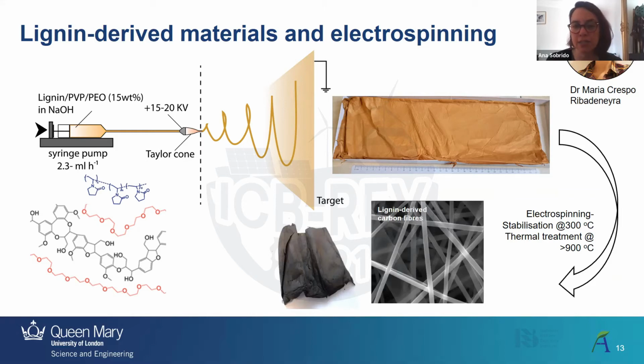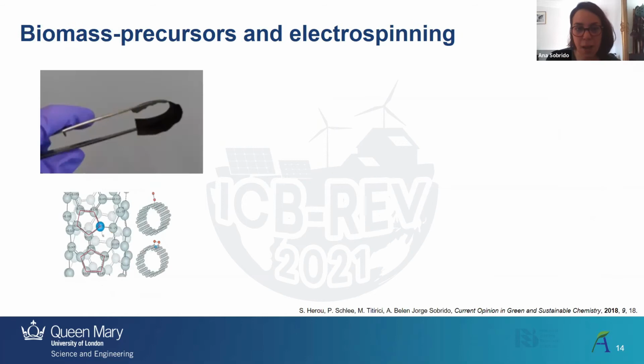The fact that we can actually do self-supporting electrodes means that we don't need to be putting an ink and spraying it onto a membrane or onto a current collector. We can just use that and assemble it in our device, which is quite handy. It saves a few steps along the way. So that's also very good. These fibers are fairly elastic, but this can be tuned depending on what amount of polymer you put and what sort of polymer you put.